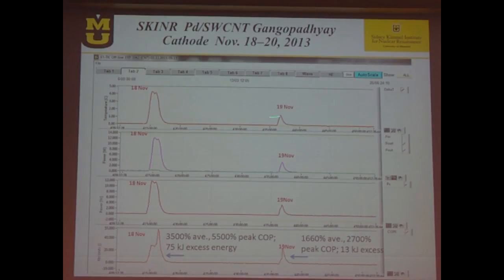Now, these are hours. So after about 400 hours that nothing happened, it started. And as you can see here, this is P in, P in net, and P out. Now, P in net is a reduction of the heat of the power of dissociation of the electrolyte, and so we are subtracting it since it's an open cell. But it doesn't matter. Even if you take P in total, I times V, without subtraction at all, you see that the input power, whether it's P in net or P in, is much, much smaller than P out. And these are the amounts of heat released. Actually, at peak, 55 times more power out than power in.